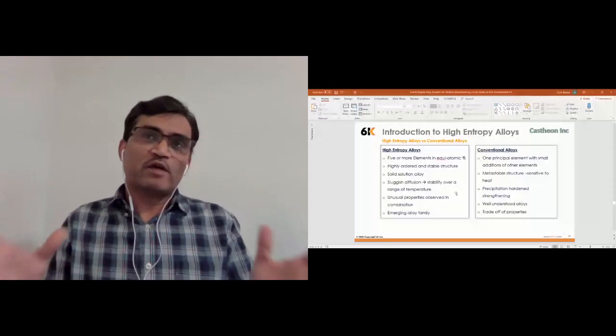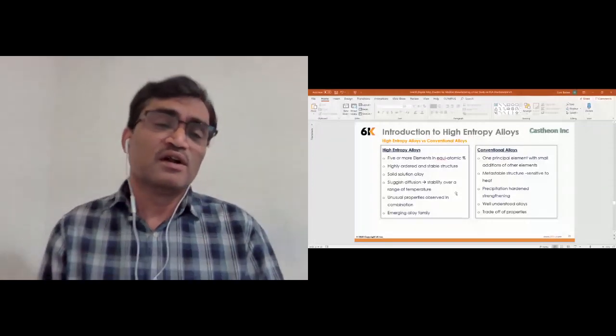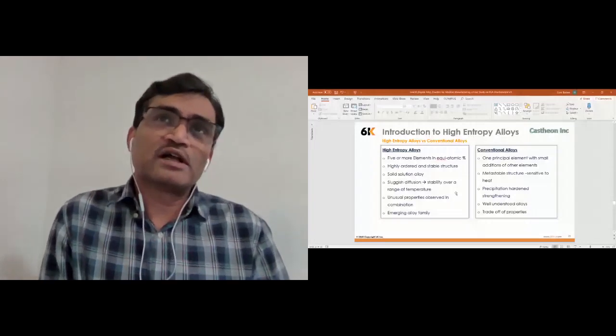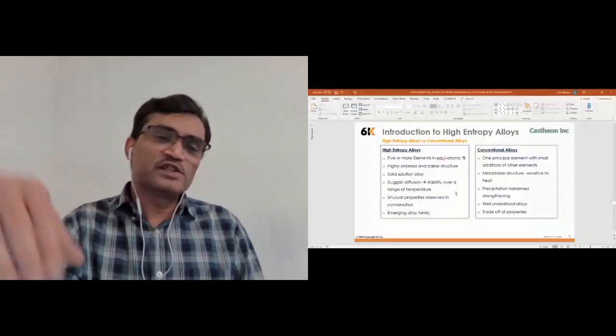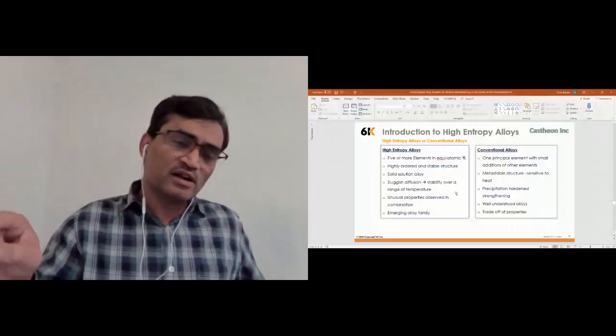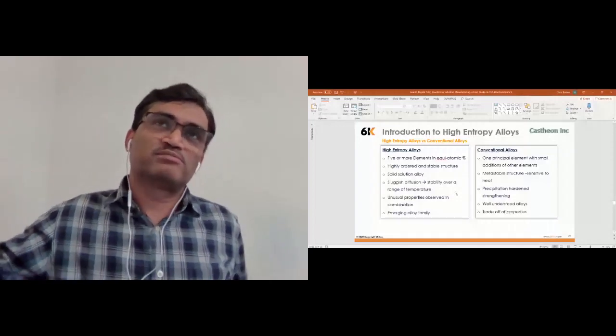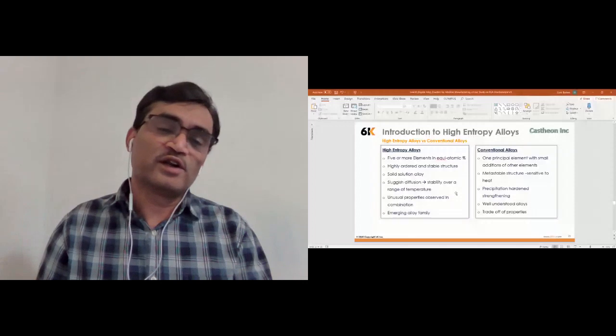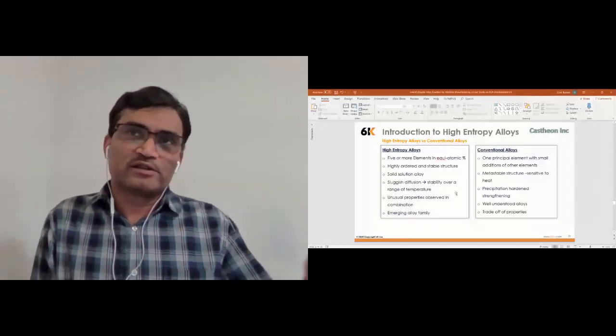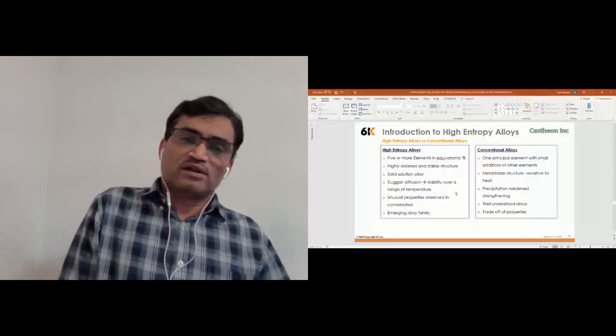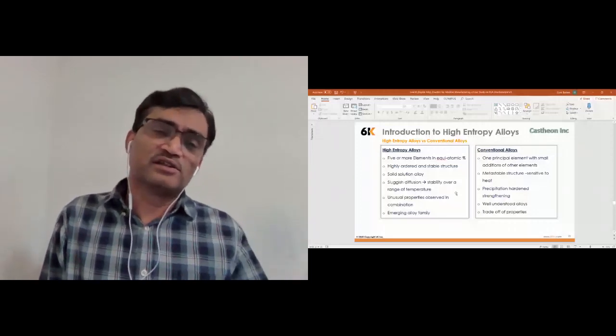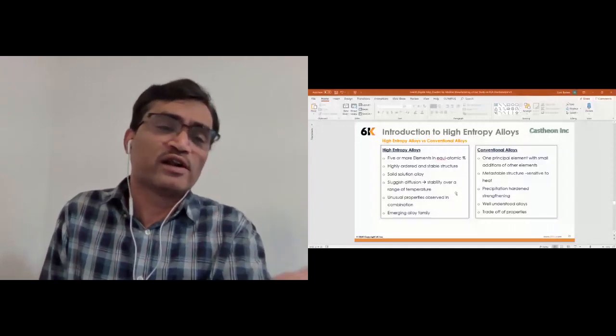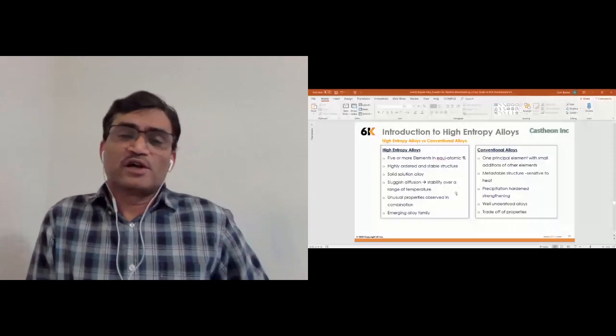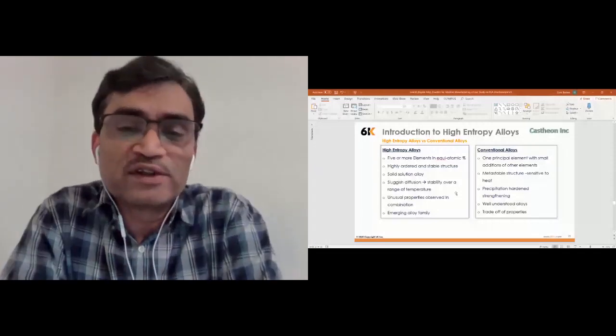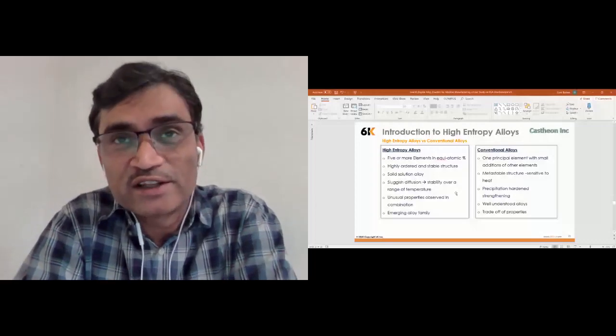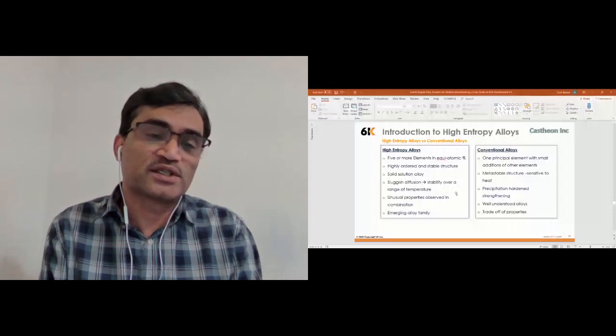That means they are all in the same composition range, and that makes it high entropy. You'll see in subsequent slides that high entropy alloys are considered as more than 1.5 R entropy alloys. So more entropy makes the free energy more negative, and the alloy becomes more stable. So these high entropy alloys are more ordered than conventional alloys, and more stable than conventional alloys. They are metastable, and very sensitive to heat, and that's why we use heat treatment to get different properties.